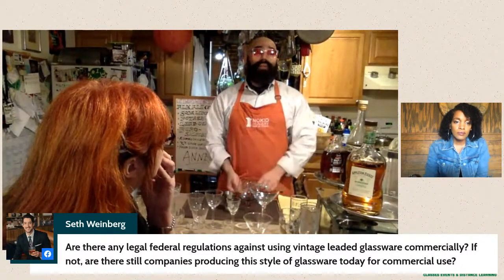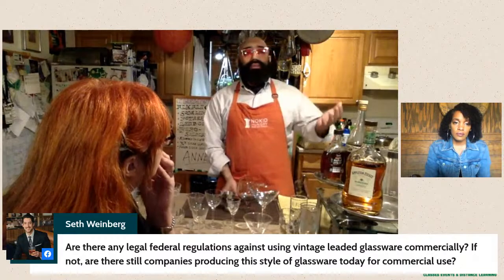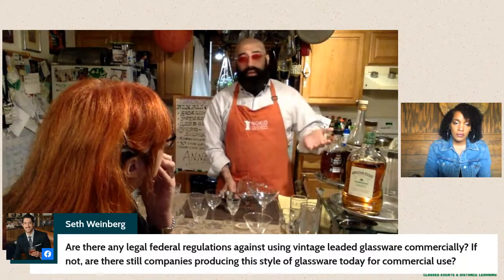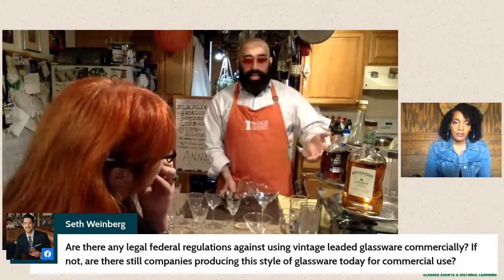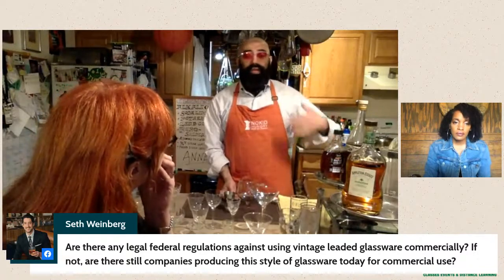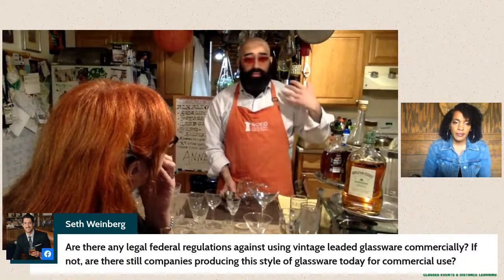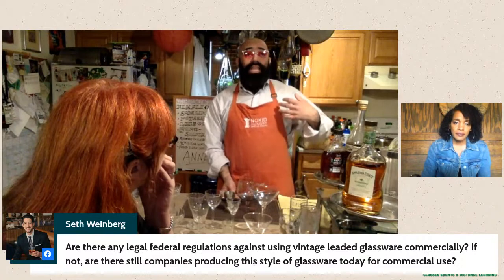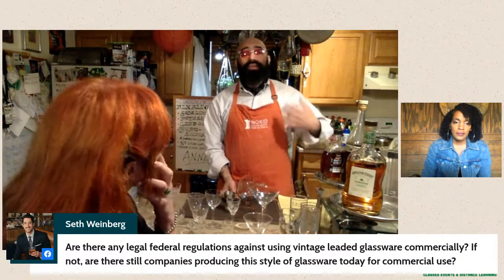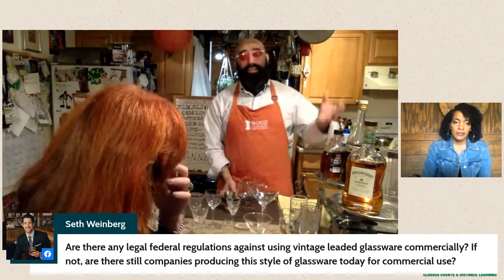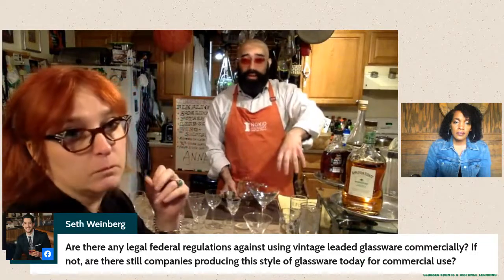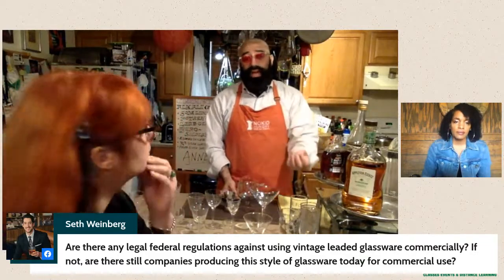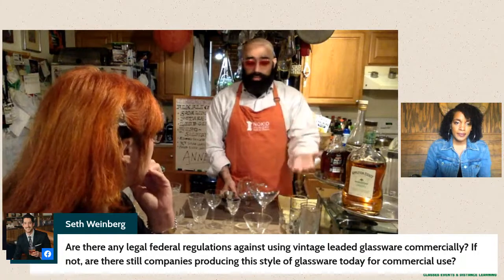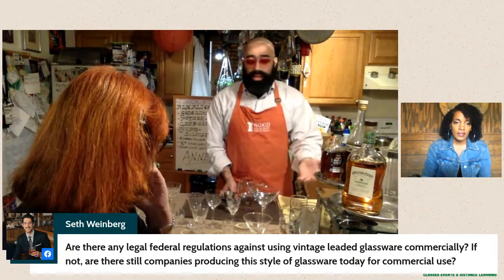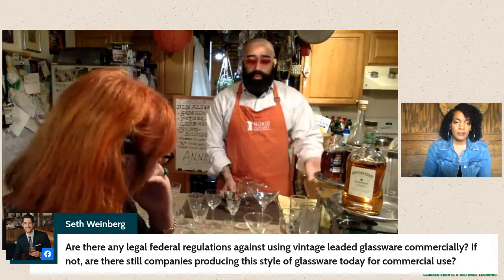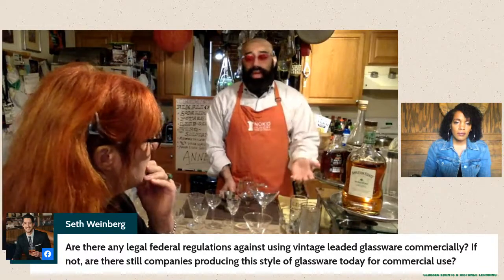But the amount that you wash it and the nature of how you wash it in terms of the heat, like if you're using a dishwasher, the drying cycle, which exposes it to very hot air, those are the things that actually potentially weaken or damage the glass. Also, the fact that it's being put upside down, like we mentioned earlier, and exposing the fine rim, like for a wine glass, you're going to be exposing that to damage, chipping, or breakage. So that's why you hand wash.